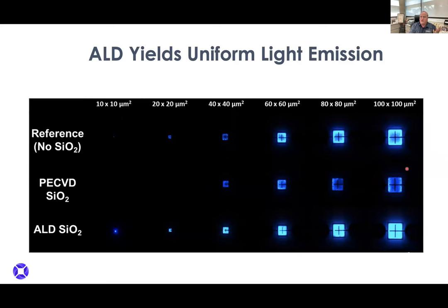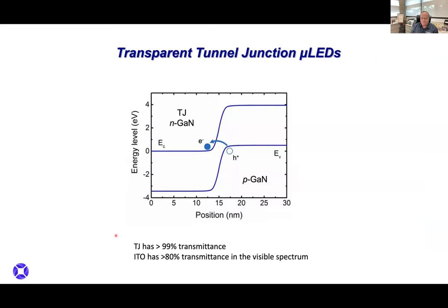And this was kind of weird, because this works great at 200 by 200, but it starts dropping off pretty quick. And we found out that this was actually damaging the sidewalls of the LED, which isn't a problem when the LED is big, like for your LED light bulb, but it's a problem when you're trying to make a very small LED. So we were pretty surprised, even ourselves, that with ALD, even at 10 by 10 microns, it was still quite bright. And so we knew that this was going to be a key technology to develop for other LEDs. So that's why ALD is now being used by almost every manufacturer that's working on this process.